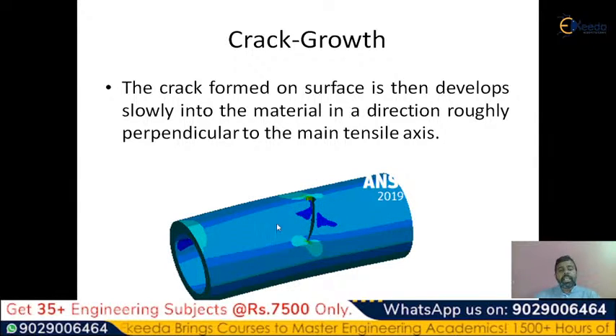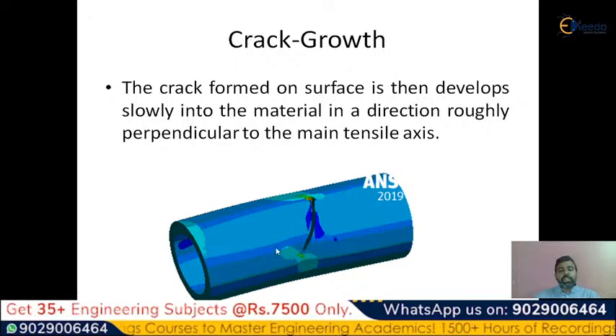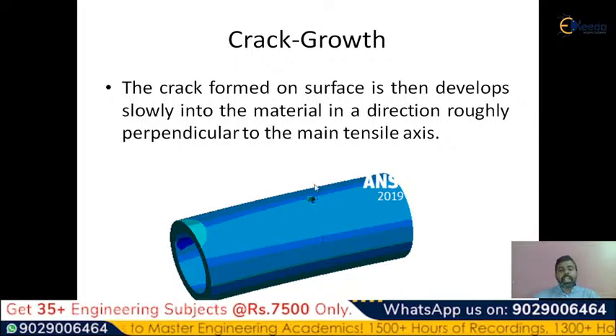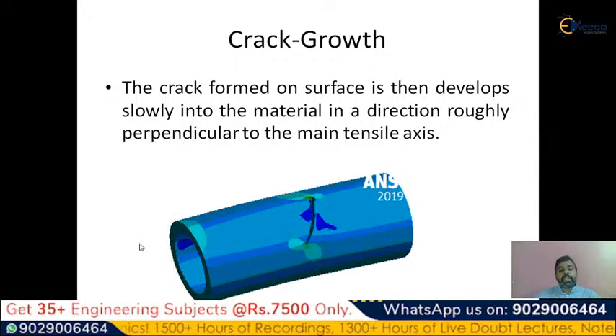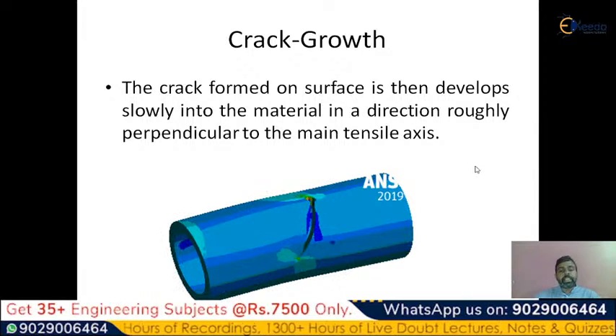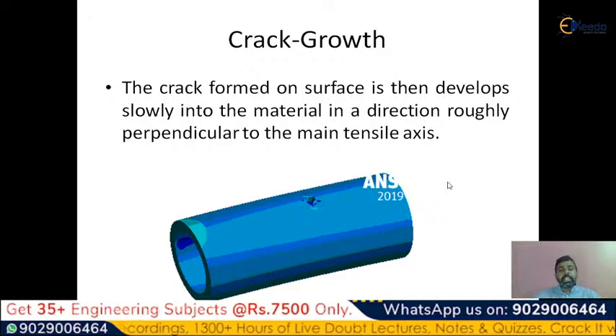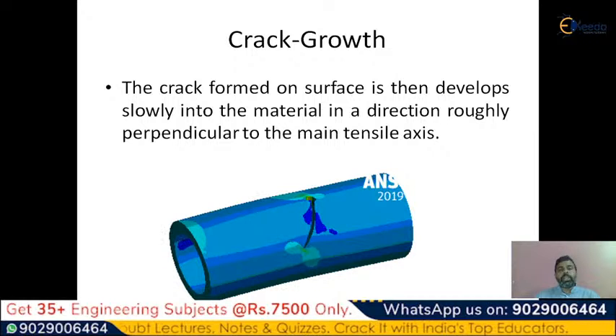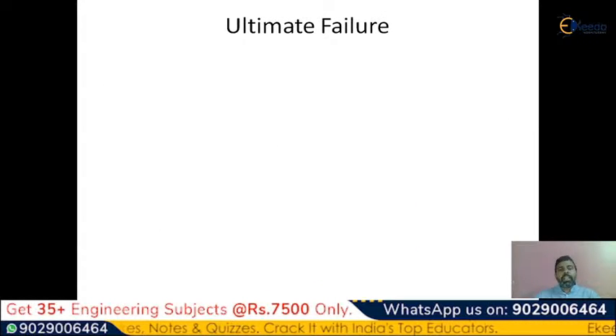So you can see the crack growth clearly in this particular shaft image, which is perpendicular in direction to the tensile axis, if you assume the tensile axis direction is in this direction. Now this is the second stage of the material, that is the crack growth, or we can say the fatigue failure second stage. Now the third stage is ultimate failure.